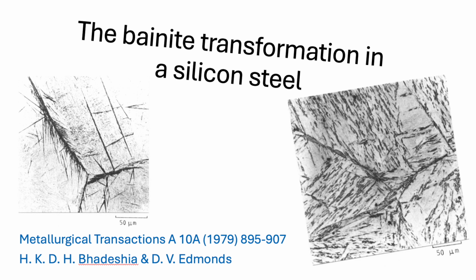Then lower bainite provided proof of carbon supersaturation in the ferrite through mechanical twinning and the way the carbides precipitated internally on multiple variants. Trapping the carbon. Trapping the carbon. And finally, the direct observation of those constant width, 0.2 micron spikes at the LB interface provided visual evidence for growth via discrete shear units.